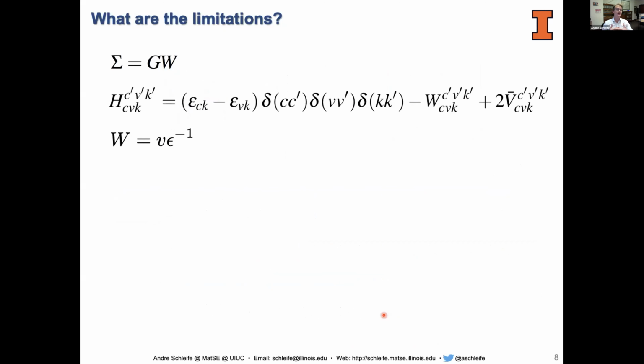I'm pointing you to those because that's, I think, where future development is either needed or promising. And I'm just recapping the most important equations here. One is this GW approximation, one is this exciton Hamiltonian. Both include the W term, and the W term specifically is the Coulomb potential now screened by your material being present. So in a bulk material, you would have to describe screening due to that material. As Christian said, near a surface, you may have very inhomogeneous screening because, in plane and out of plane, the screening is different and so on. So epsilon is a tricky quantity.